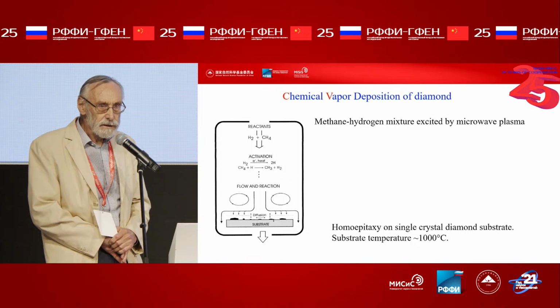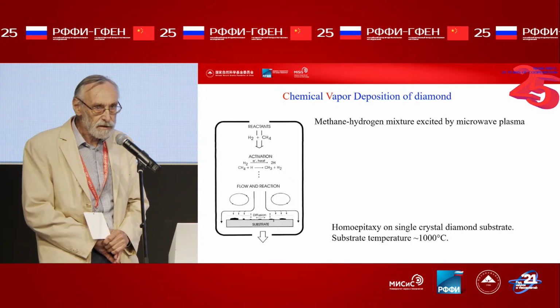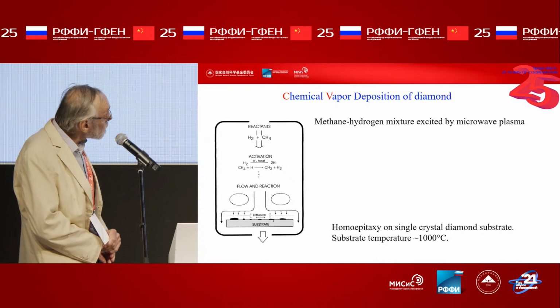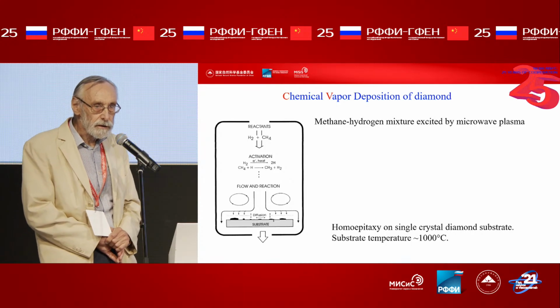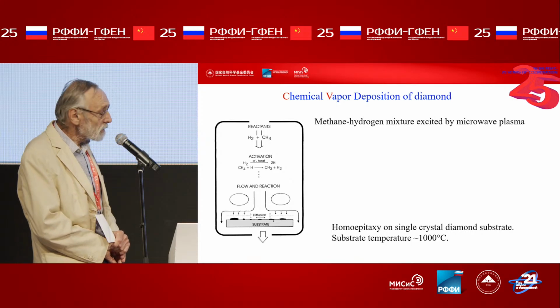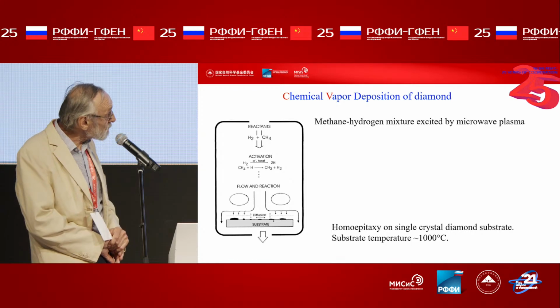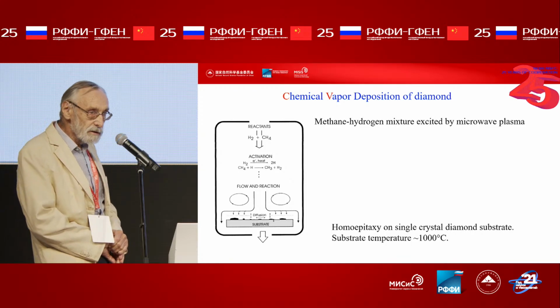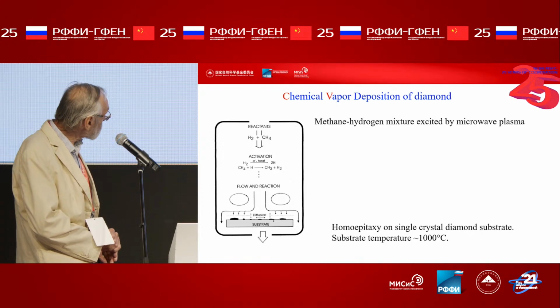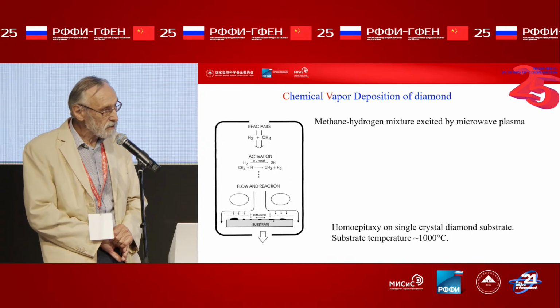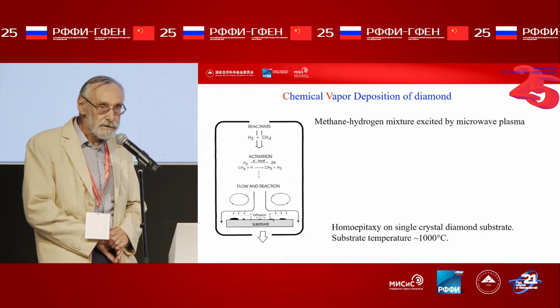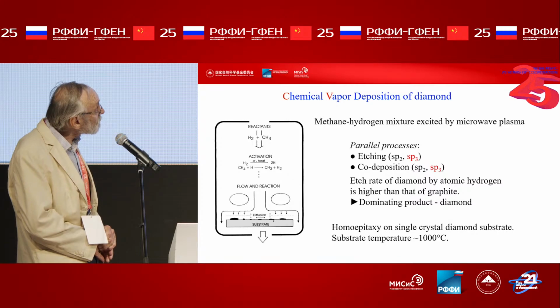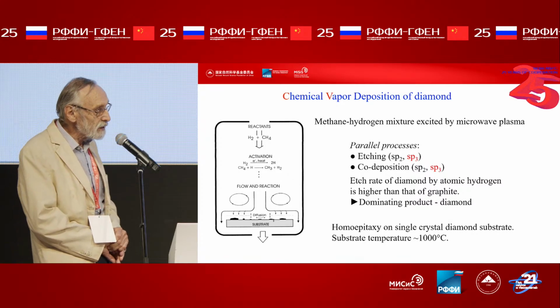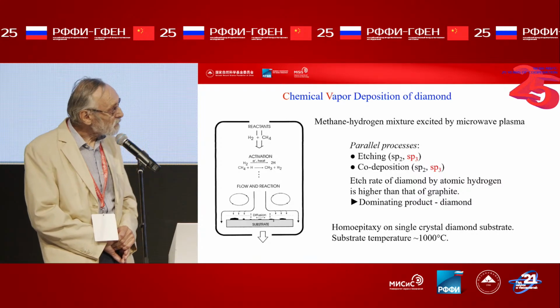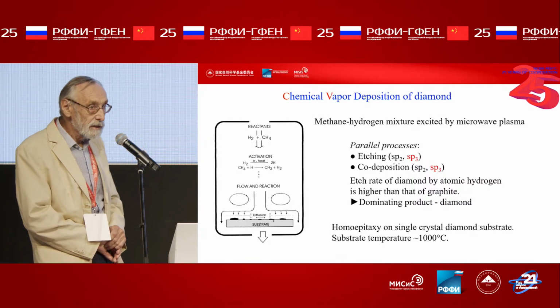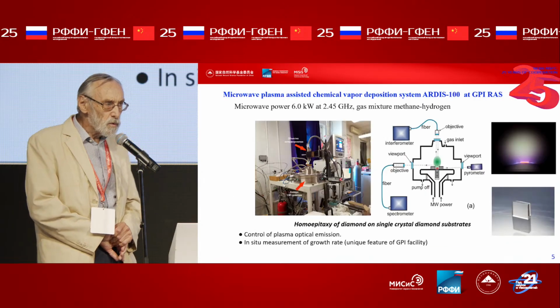So, just let me remind you of the principle of chemical vapor deposition. We have a vacuum chamber. We introduce two gases, only two, hydrogen and methane. Methane is the carbon carrier. And diamond is deposited in such conditions on a hot substrate. Hot means about 1,000 degrees C. Next slide, please. And hydrogen is needed to continuously clean the surface of the deposit, removing graphite. Next slide, please.